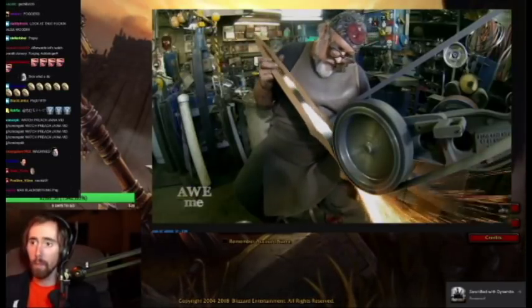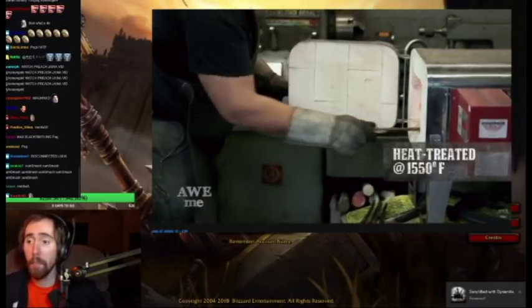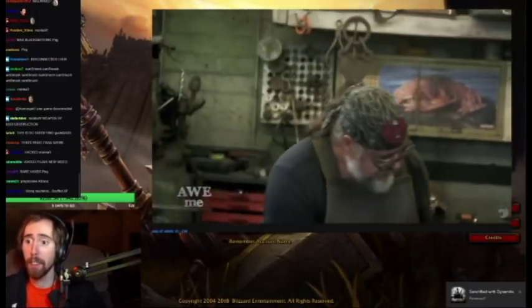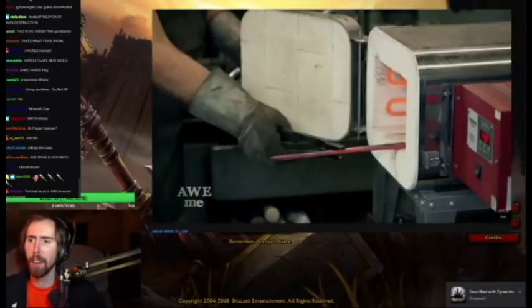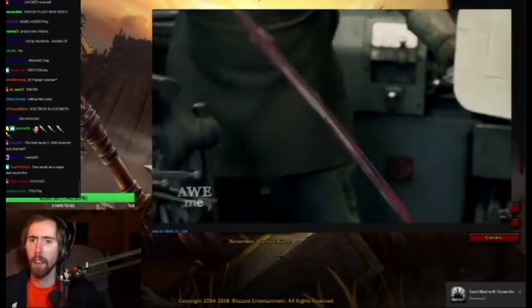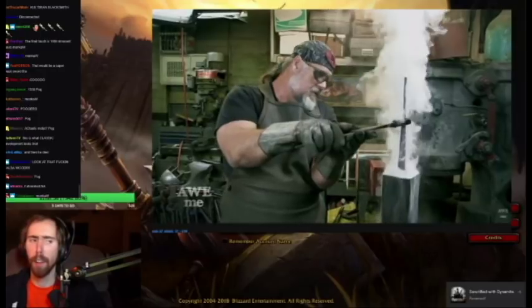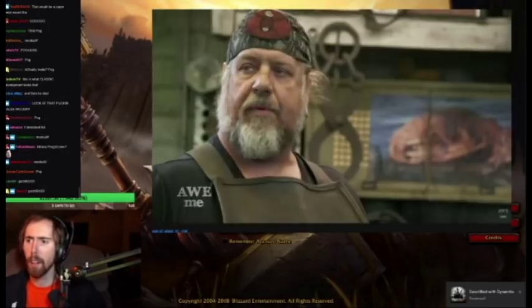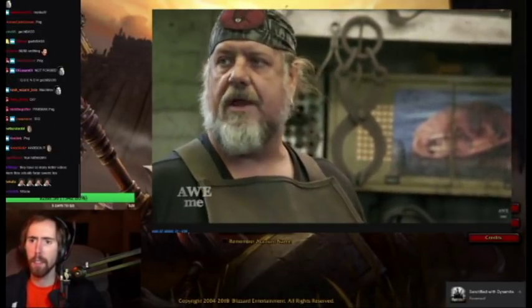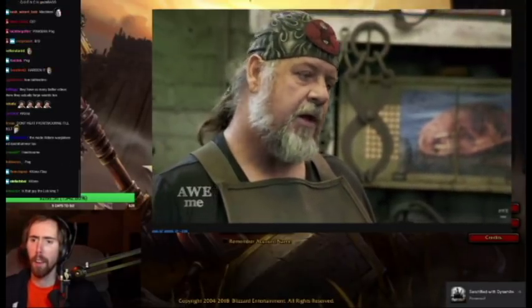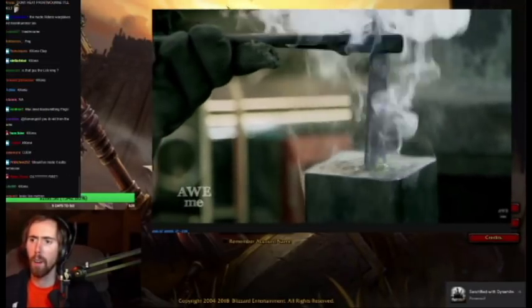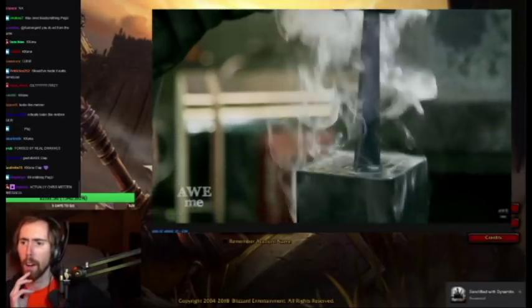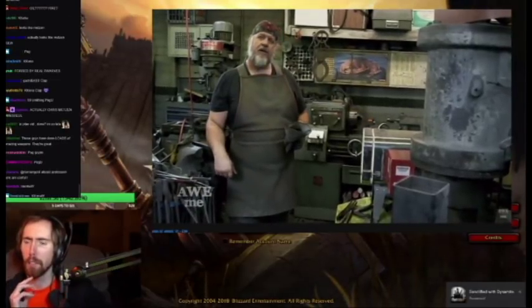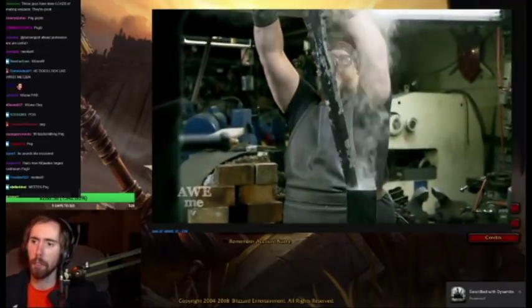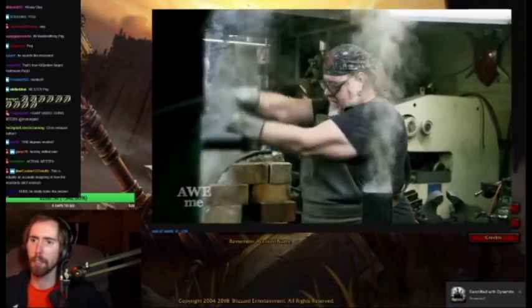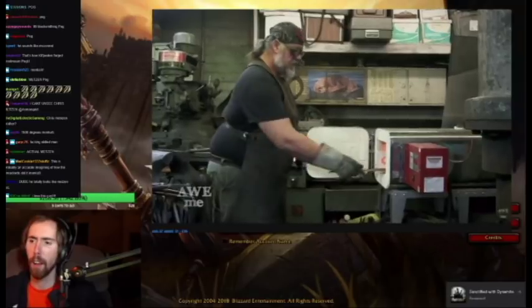At that point, we put the blade into the electric heat treating oven and brought it up to about 1550 degrees and quenched it into heat treating oil to harden it. The oil I'm using is a Park 50 heat treating oil. It's a professional heat treating oil. It's very expensive. You can't buy it from the general public. You can notice here I'm putting a piece of metal in the oil at 1500 degrees. It's not catching on fire. See, they should have done this with Thunder Fury. I now need to temper it in the electric oven. Put it in there at 600 degrees for about 6 hours.